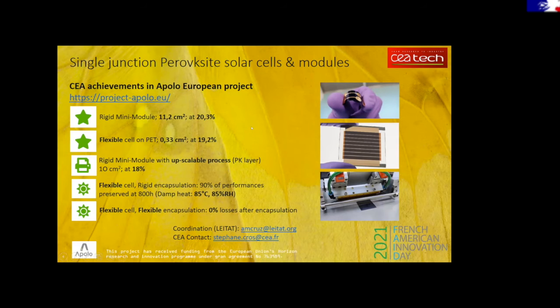Globally in the lab, we achieve very good numbers. For example, 20%, but with 11 square centimeter substrates, which is pretty high. In 2020, it was, we could say, like a world record, considering the combination of surface and efficiency. Recently, we also did very good numbers with PET-based solar cells. As I said, it is possible to process this material at a low temperature.